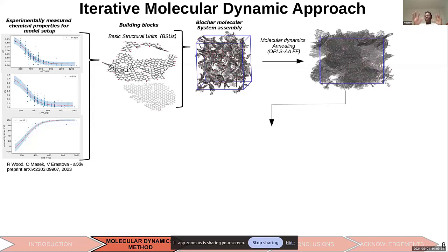And we're able to condense the material from this process, which is a simulated annealing. We heat the material at a very high temperature, enabling the various structural units to sample the energy space, and then we cool it down. So we move from 1,000 to 700 to 300, and that's how we're able to cool down the material until it gets to a very solid state that's more or less equilibrated.